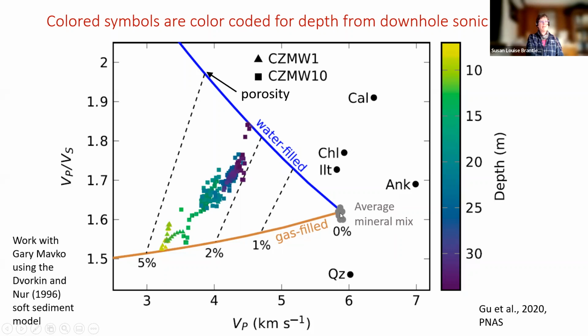So if there's no porosity in the rock, this is where it should plot on this P wave diagram. If there's porosity and it's 1% and it's water-filled porosity, it would plot here. And if it's 2% porosity, it would plot up here. And so very consistently, the data plot at a little bit more than 2% porosity, which we've measured in the rocks downhole, water-filled.